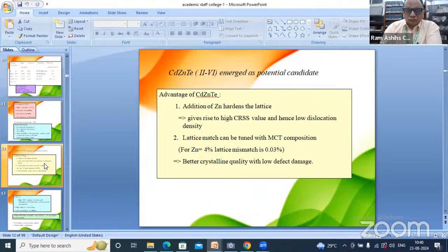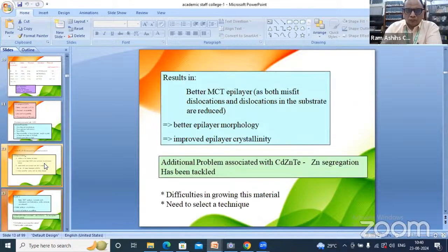And large diameter single crystal or large grain size is the main impediment of the growth technique. Nowadays, cadmium zinc telluride has emerged as a potential candidate for the substrate material. Here, zinc with 4% is suitable for MCT epitaxy layer growth, and this gives us better crystalline quality with low defect damage. And zinc segregation is resolved with in situ annealing of the crystal during the growth process, giving uniform distribution.